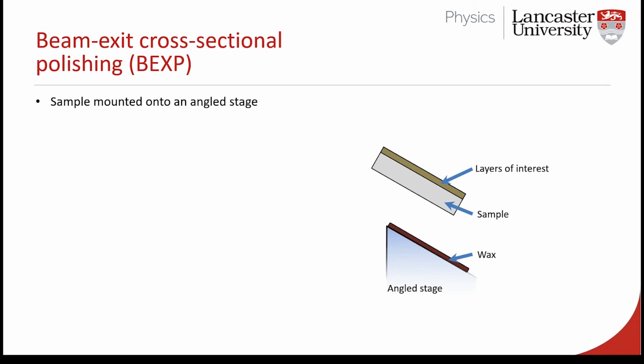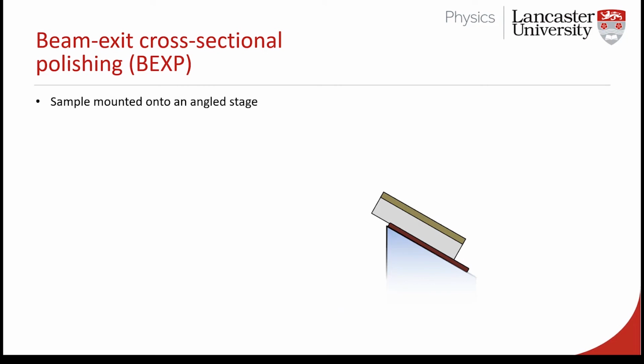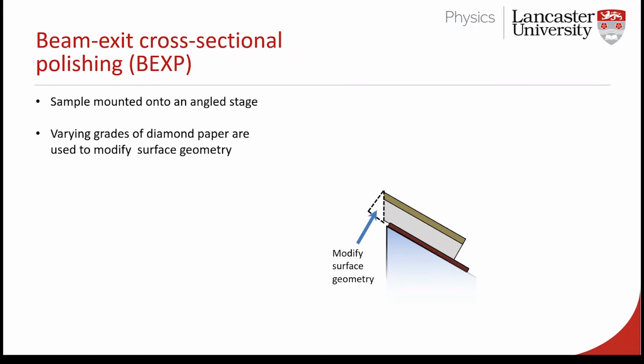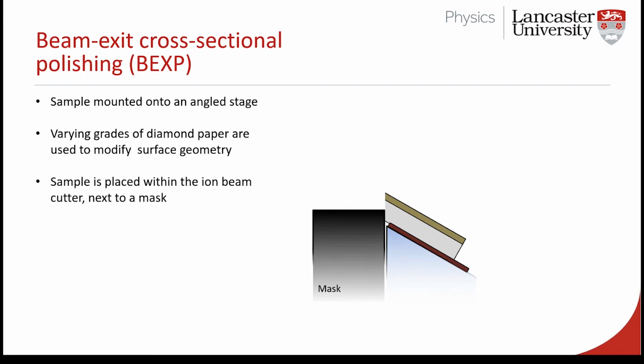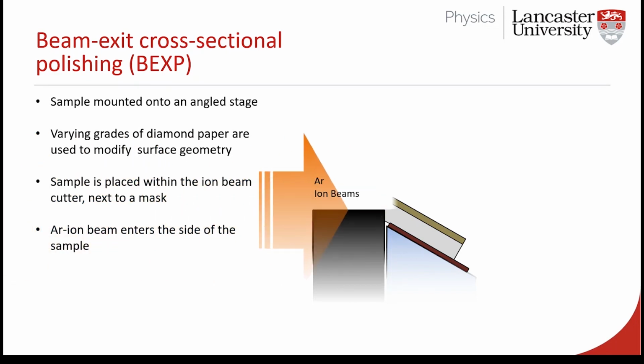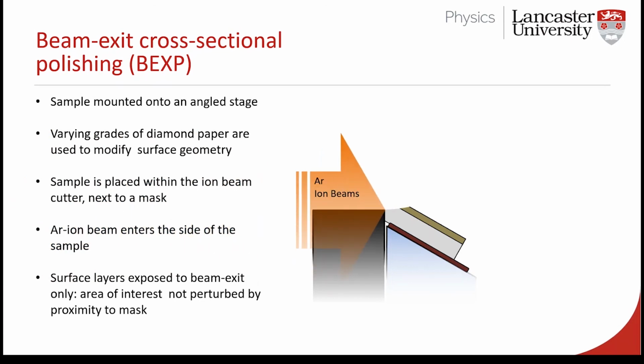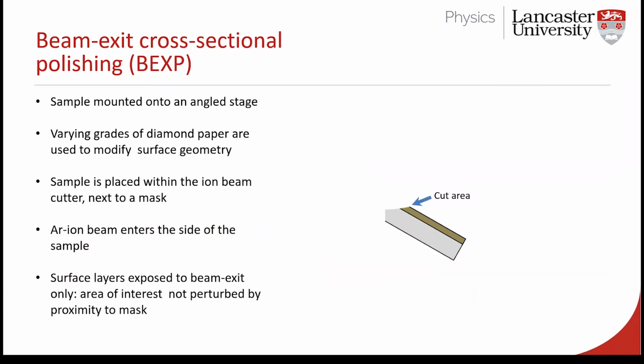So how does this work in practice? We take our sample, and we may have a thin layer of interest on the surface. It may be a buried layer. We'll mount that on our sample stage at an angle. It then gets sanded down, so it's approximately flat geometrically to that angle. It's then protected with a mask. This is done under low vacuum. And then the argon ion beams are used to mill across that surface. So you can see now that interface between that surface layer and that substrate has been elongated. We've stretched it out with a simple bit of geometry.